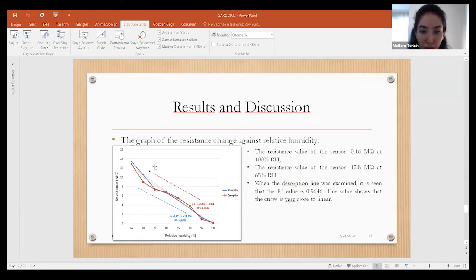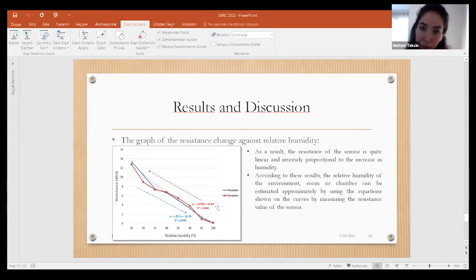For the desorption line, the resistance value of the sensor was measured as 0.16 megaohm at 100% relative humidity, and the resistance value of the sensor was measured as 12.8 megaohm at 65% relative humidity. When the desorption line was examined, it is seen that the R-squared value is 0.96. This value shows that the curve is very close to linear again.